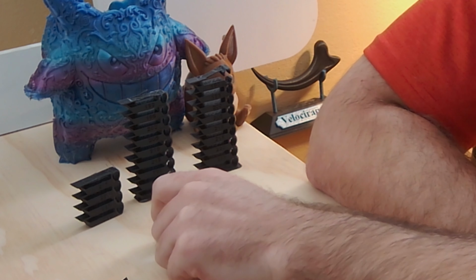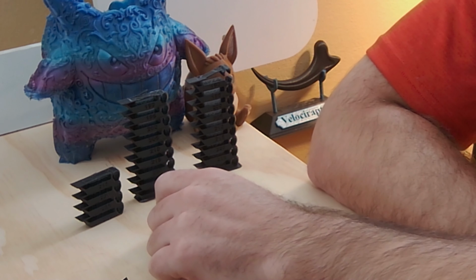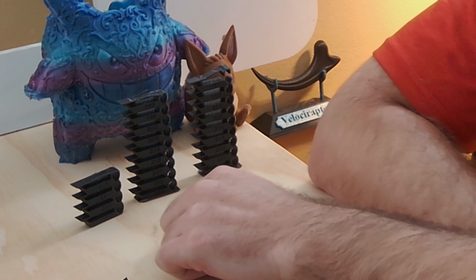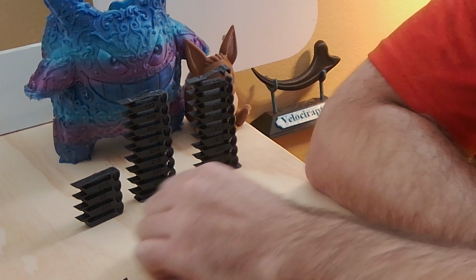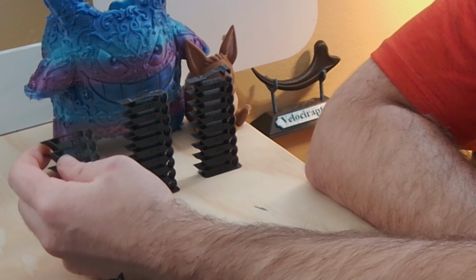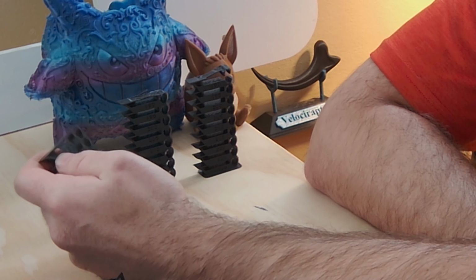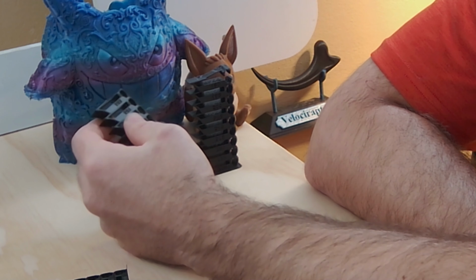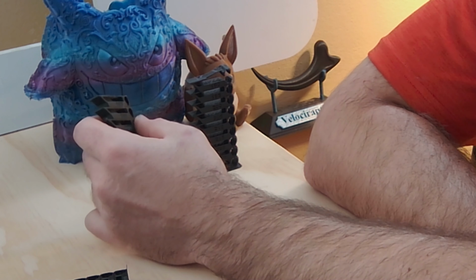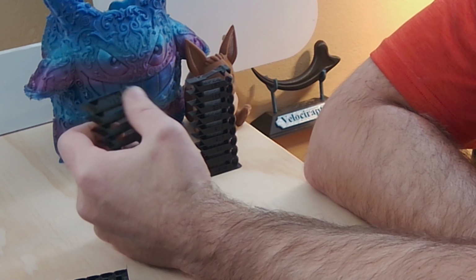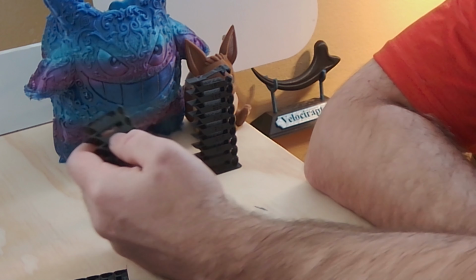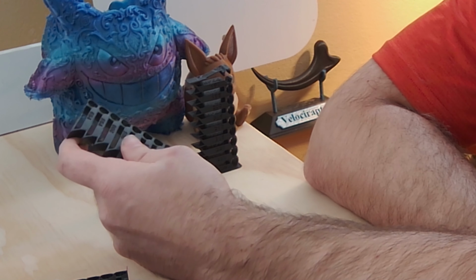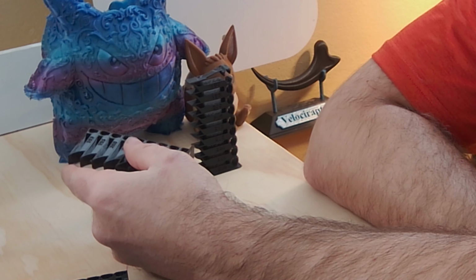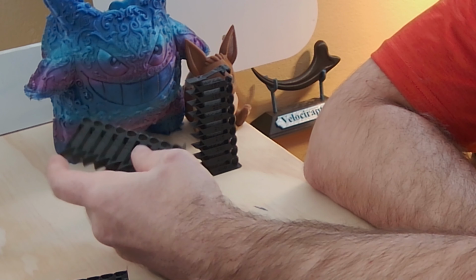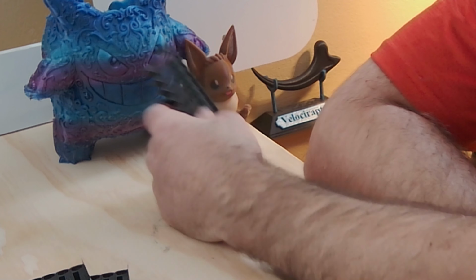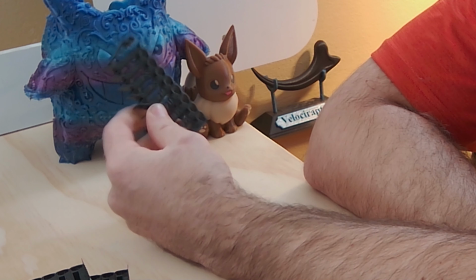Now we go into the Hyper. A lot closer results. Hyper has been known to not be as strong, or high-speed filament has been known to not be quite as strong as its counterparts. With the hardened nozzle, 215, which coincides pretty close with the other one. With the nickel copper nozzle, got up to 190 here, so it was stronger with the nickel than it was with the Red PLA. So there is some strength there. And then same exact results, 195 with the Hyper Diamond.